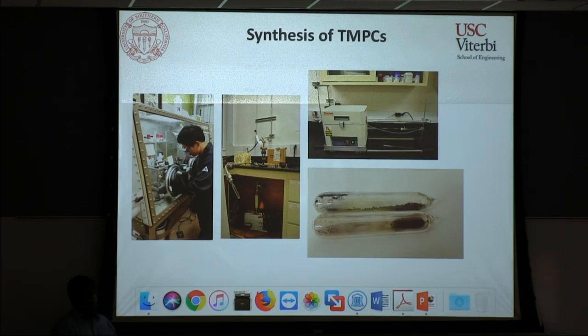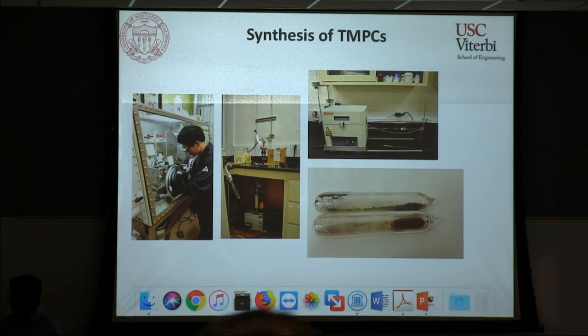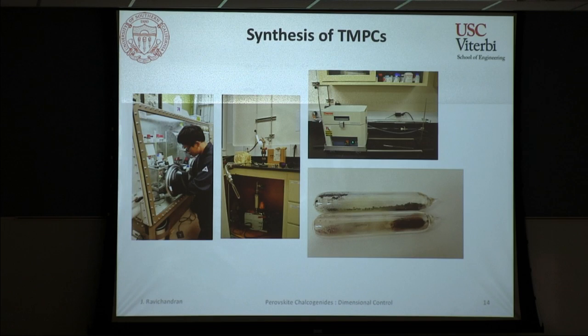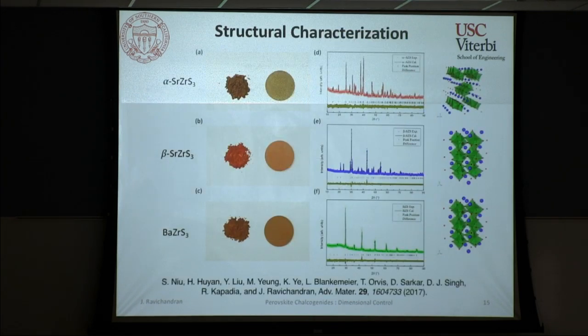Luckily, when we started doing this, we found that within a day or two of cooking, our materials started to crystallize and they looked really homogeneous visibly. And we started characterizing them using diffraction, and we found that we were able to stabilize the barium zirconium sulfide, BaZrS3, in the distorted 3D network connected corner-shared perovskite phase.